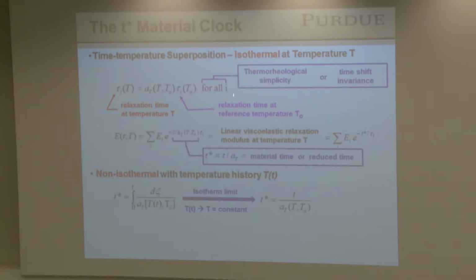So that's what happened when it was isothermal. This is the generalization when you have non-isothermal response. So this says a sub T is a function of temperature, which is a function of time. But notice if temperature were constant, a would be constant. It would come outside the integral. We could do the integral, and we get t over a sub T. So we recover this t star that we had up here for the isothermal case. This is just a generalization for non-isothermal material. All of the effects of temperature history are contained inside of this a function.